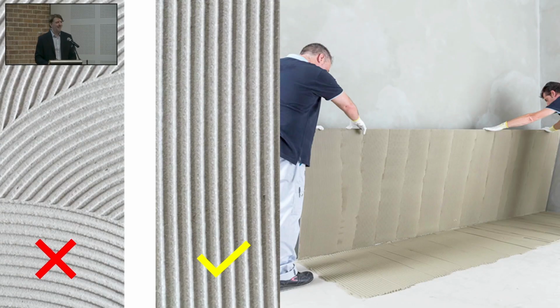But in this case, you see here, the ribs, the lines of the adhesive on the back of the tile and on the floor, are in the same direction. Same direction, and according to the shorter size of the tile. Because when you lay them down, if the lines of the adhesive cross each other like this, the air will be trapped under the tile. In this way, instead, the percentage of air that will be trapped under the tile is very minimal. And when I press the tile once I finish, the air will go out in the shortest direction possible.